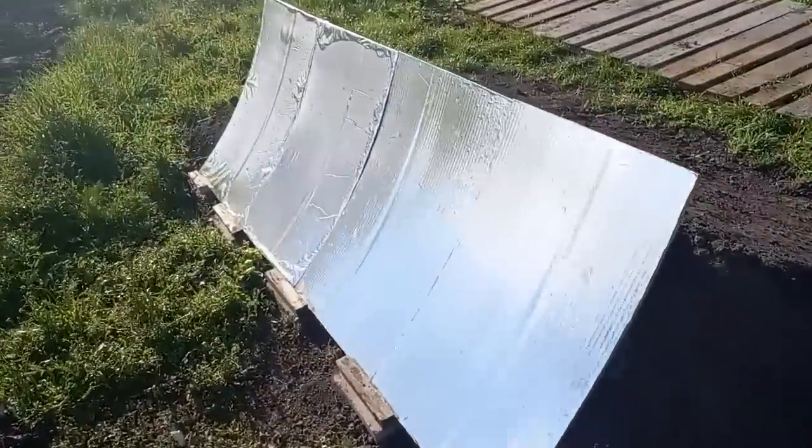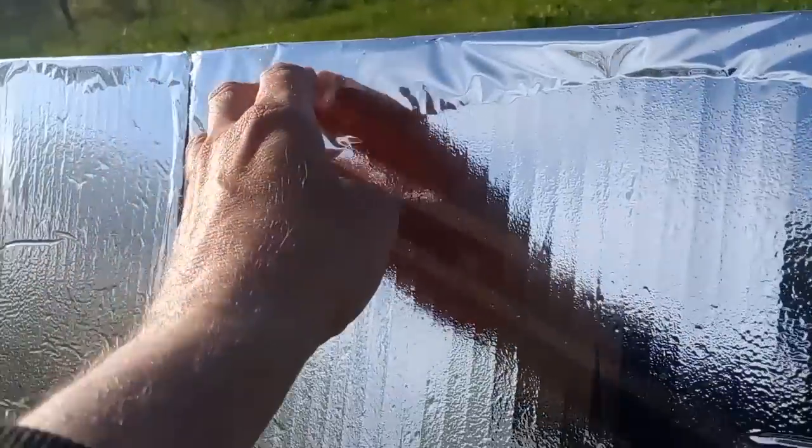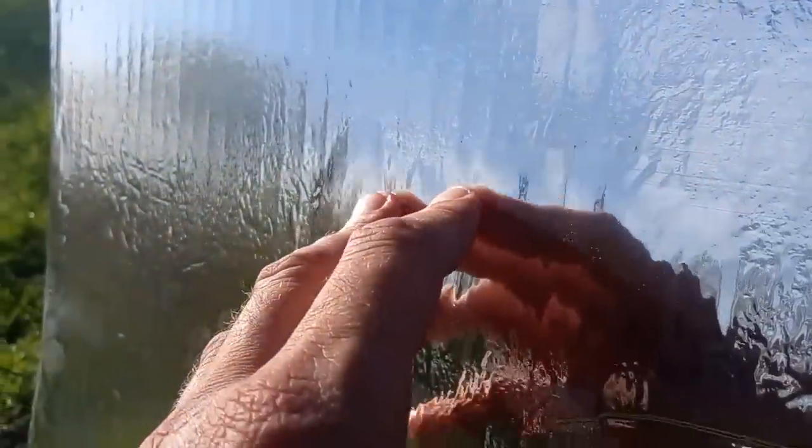Now I will show you two of my mirrors, which were made by hand. We see that the cement fixed my reflective film poorly — for example, here the film has already left the concrete surface. After a few days or weeks, the film will leave almost the entire surface, and maybe someone will someday offer a solution to the problem of bonding polymer films to cement.